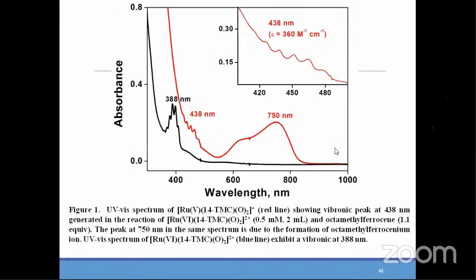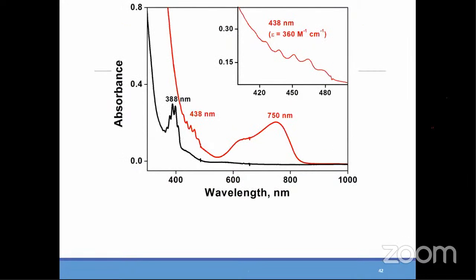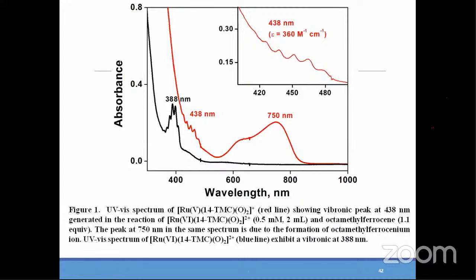When we did that, you can see here this is the ruthenium(VI) dioxo intermediate at 388 nanometers. On addition of ferrocene or octamethylferrocene, somewhere around 438 nm you again get a vibronic peak, and the 750 nm peak is nothing but the ferrocenium ion. After giving the electron, it forms a ferrocenium ion, so that peak corresponds to that. So this compound was very well characterized. It again gives vibronic spectra.